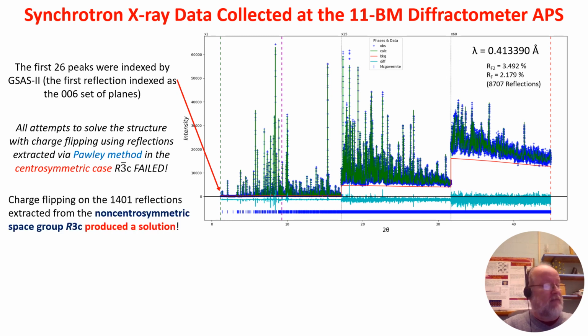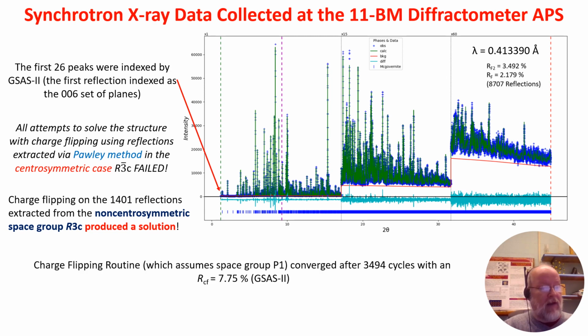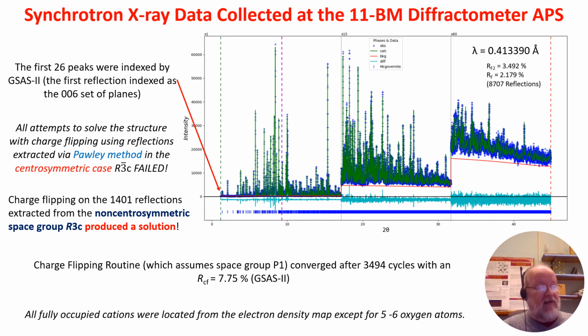So then what we did is we extracted the data again, but assuming we're non-centrosymmetric. We took those data, put them in the charge flipping routine, we let it go, and we're amazed. After 3,494 cycles, it converged with an R of 7.75%. It solved this huge crystal structure. We looked at the electron density map, and we found that all the cationic sites that were fully occupied were located, and almost all the oxygens, except for about 5 or 6 of them, were located. This was done with powder diffraction data. A couple decades ago, impossible.